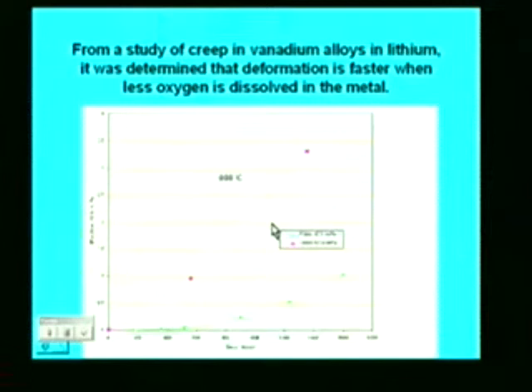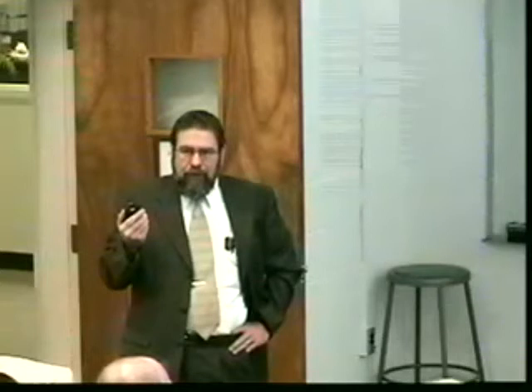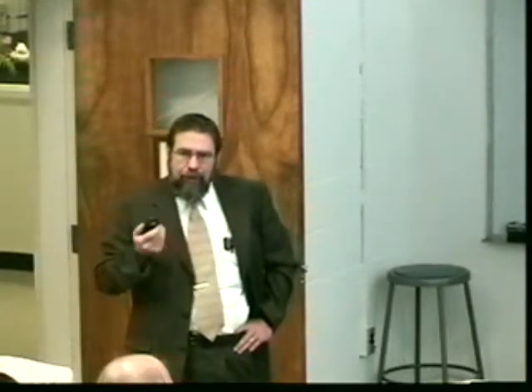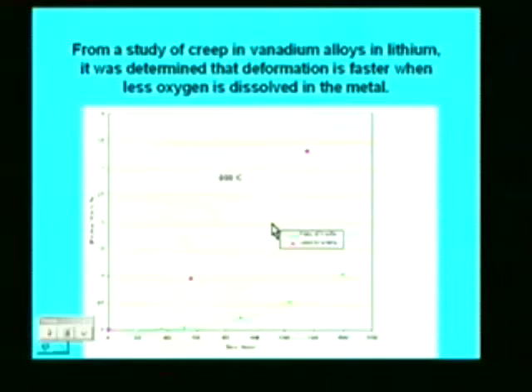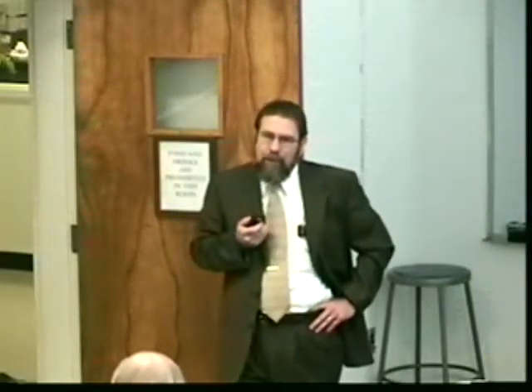Well, from the study, we said that in the case of lithium in contact with the vanadium, oxygen will preferentially accumulate in the lithium. So here we have creep strain, done with pressurized tubes again, done in the case of vanadium in lithium, and the green curve is vanadium in a vacuum. And you can see that the creep rate is much higher in the case where we don't have impurity atoms impeding the dislocation motion. So it's a softer material when we remove the oxygen, and we get a higher creep rate. And needless to say, if you're going to use this as a structural material, you better know what the creep rate is.